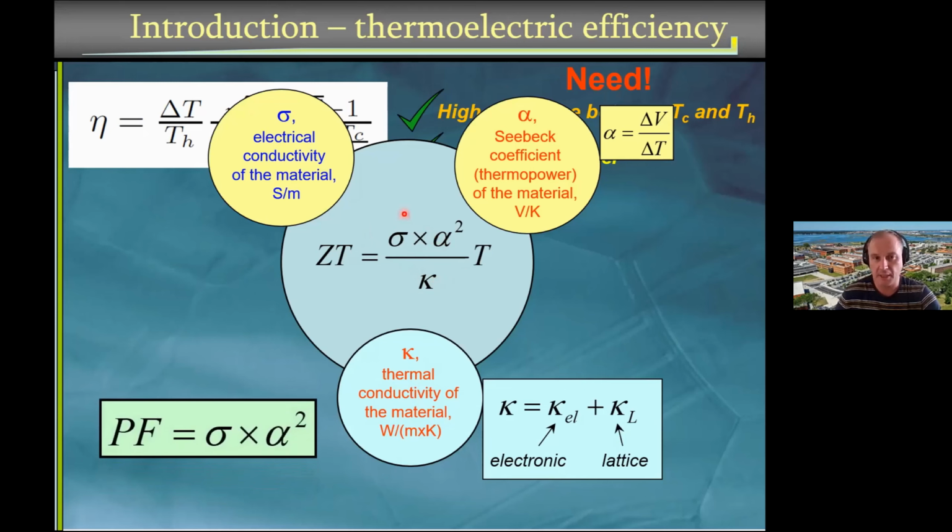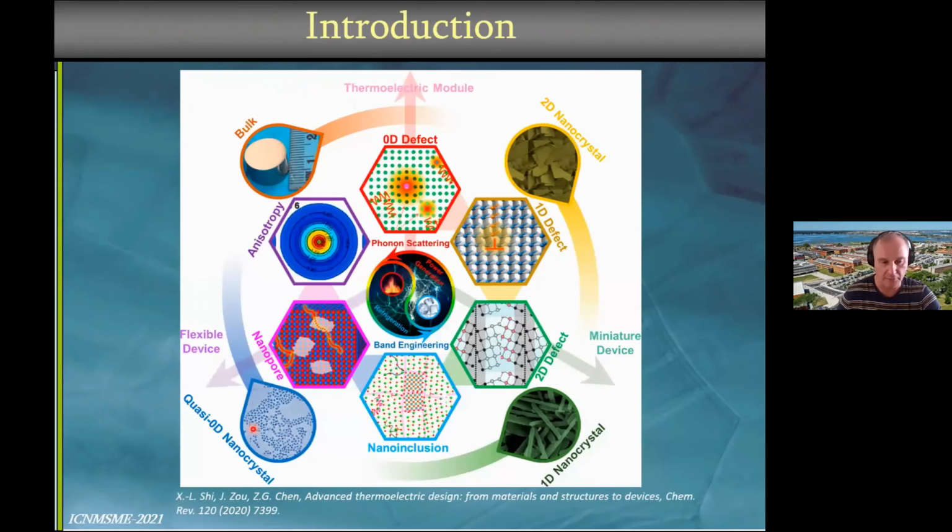So sometimes we can compare the electrical performances of thermoelectric materials using the so-called power factor, which is a product between the electrical conductivity and the square of the Seebeck coefficient.